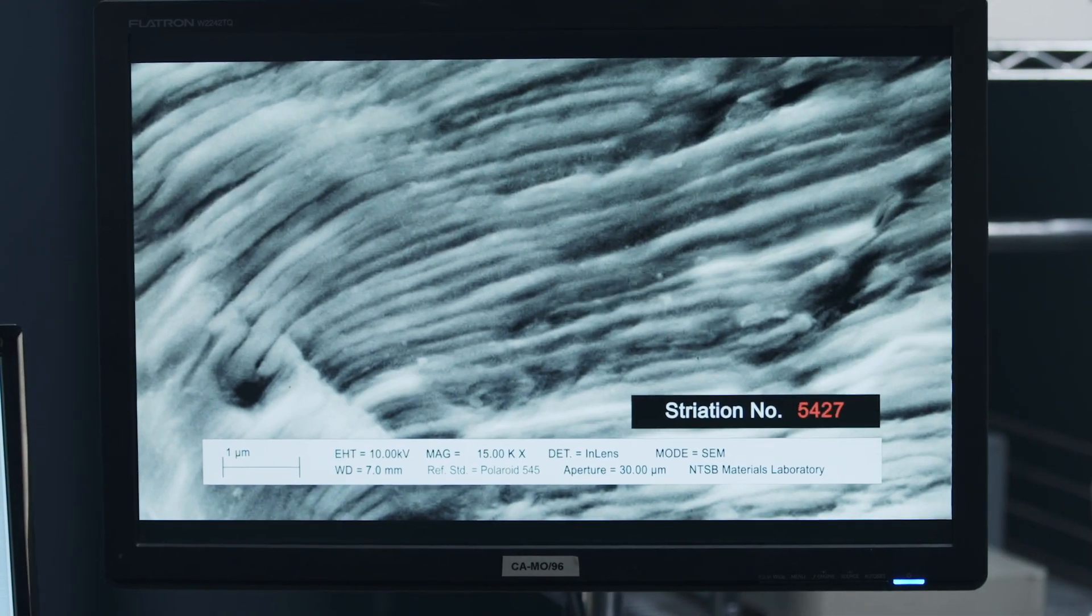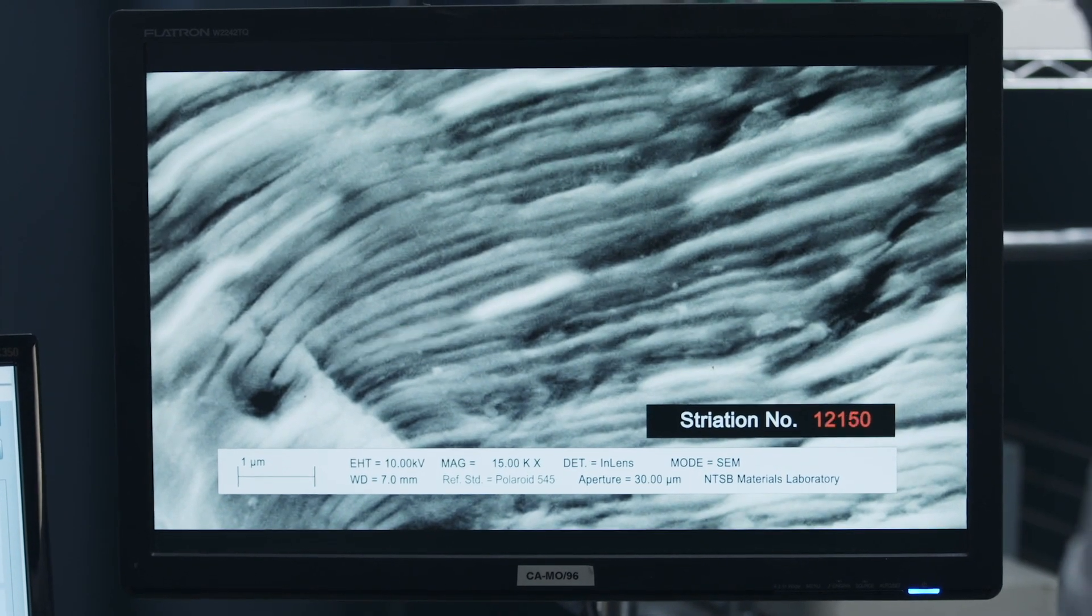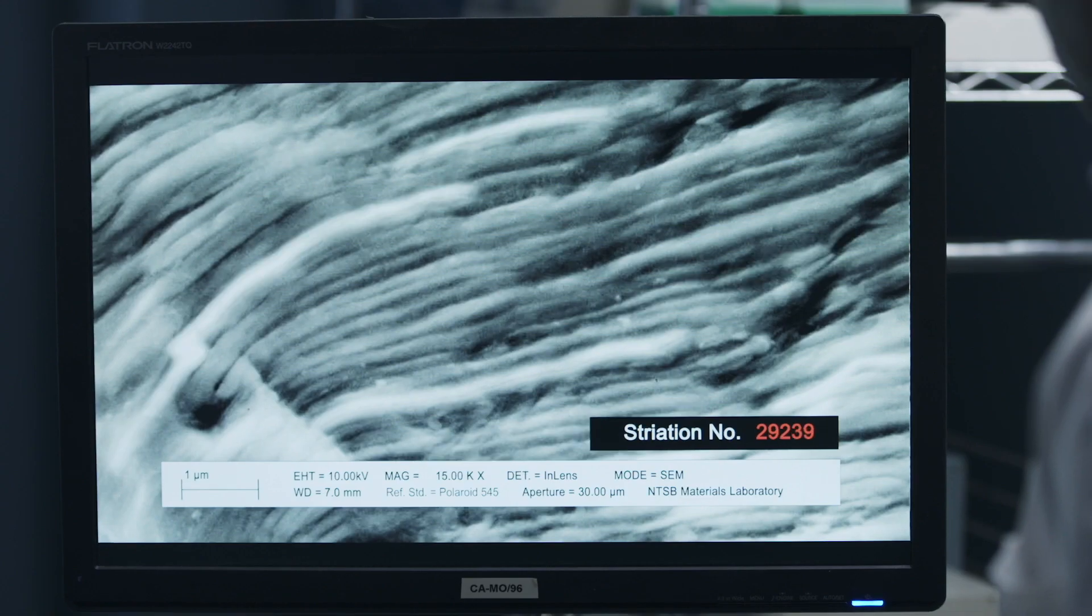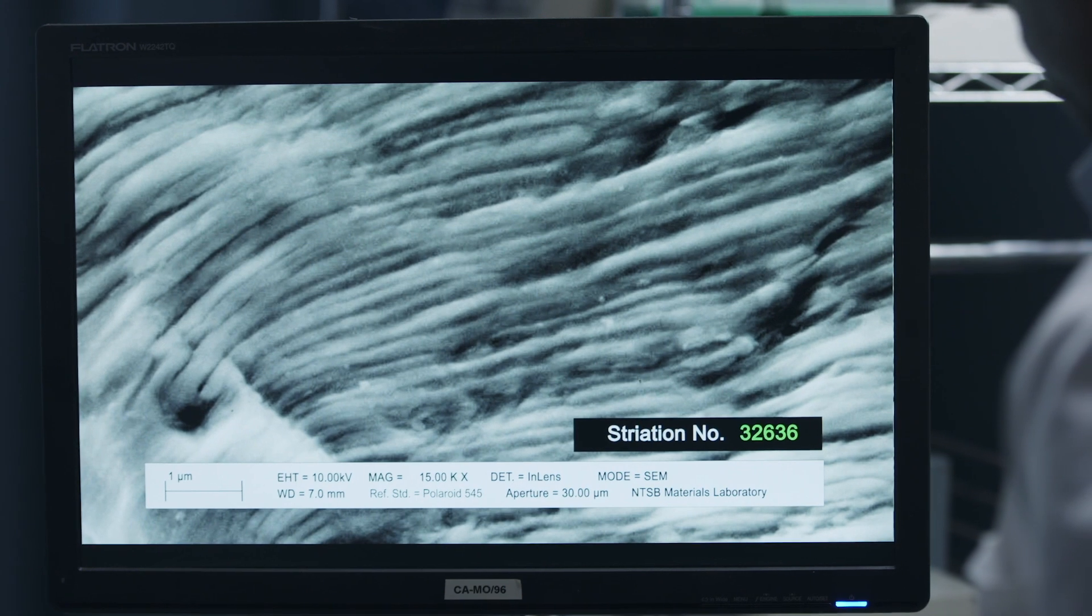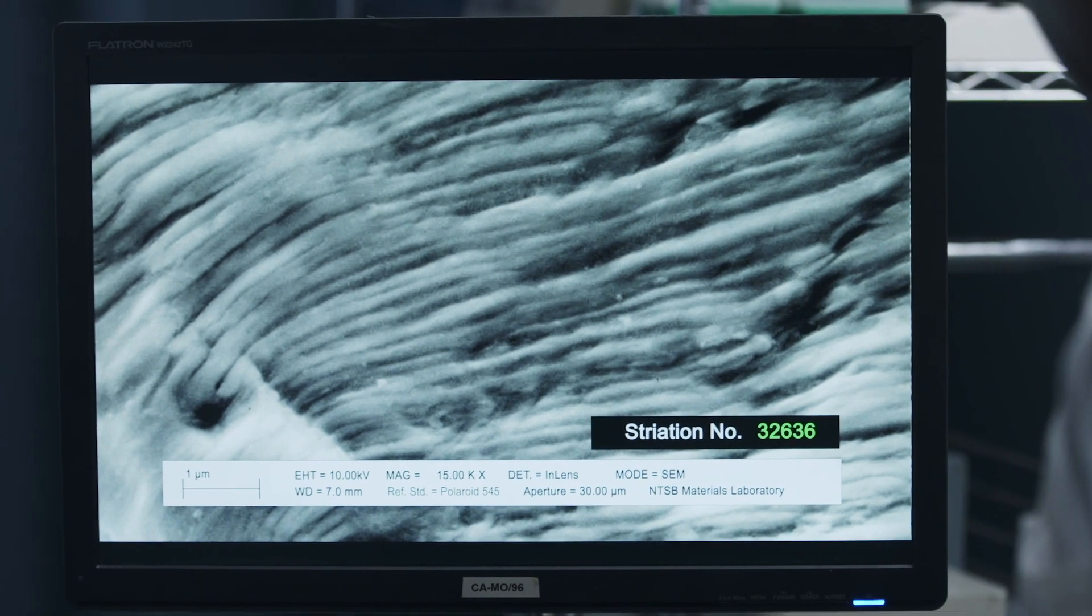Investigators tally the striations on the fractured blade. That means counting tens of thousands of microscopic marks on a tiny piece of metal. There's over 32,000 striations.